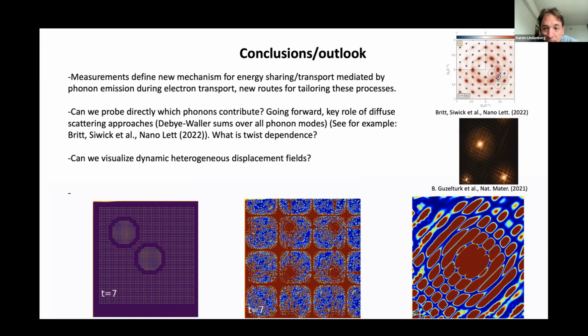processes in these systems. And we've been thinking about this from a very broad perspective, with respect to the hybrid perovskites, thinking about inelastic scattering processes and diffuse scattering processes to get information on which phonon information, which really underlies and is going to be key going forward in terms of connecting to that theory.